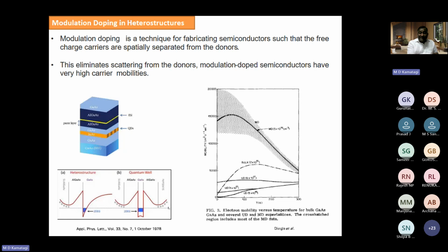What happens when the two-dimensional electron gas is far away from its donor impurities? This eliminates scattering from the donor. Therefore, modulation doped semiconductors have very high carrier mobilities. For example, modulation doped gallium arsenide has 3 times the mobility compared to the uniformly doped. This is uniformly doped and this is bulk gallium arsenide, which has almost a 3 times mobility.